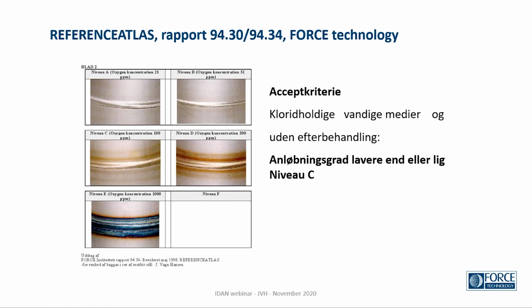But to have a tool to inspect if it's above straw or below, for many years since, we have had a reference, a report with reference pictures to sort of say we need to have something which is below the straw, and we defined by corrosion test that this was the limit. Above that, we would have sensitive surfaces to corrosion, and this one and below would be almost unaffected by the weld process.